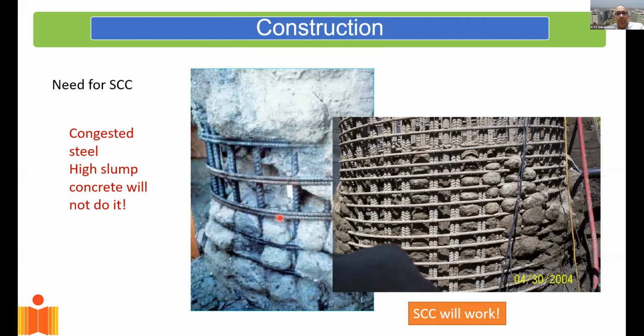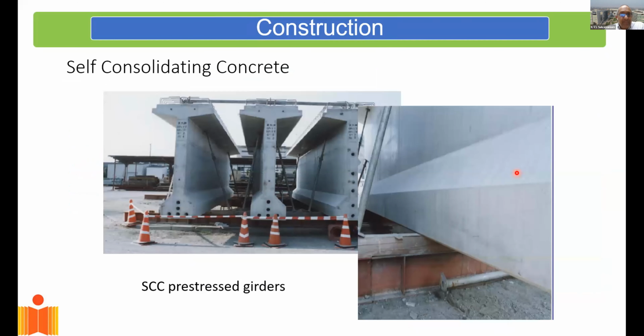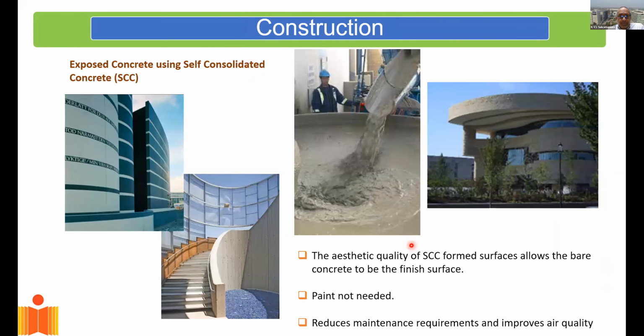Now, just another example of a cast in situ pile, and you can see the concrete just did not penetrate. This is high slump concrete, but it got stuck at these openings in the rebar. So at that point of time, self-consolidating concrete was researched, and now we have this concrete that can flow. It levels itself. It basically finds its level just like water. That is only possible through rheology control of concrete. And today we are producing a lot of self-consolidating concrete.